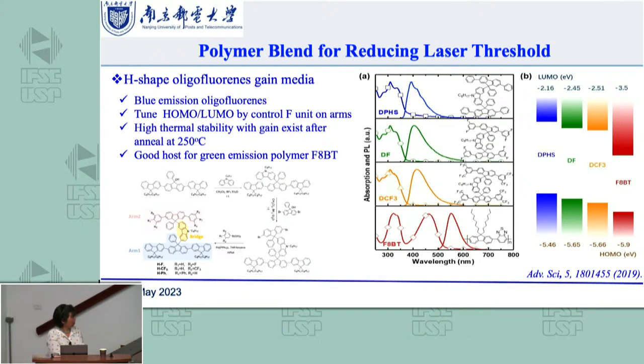And another thing is, because we have the H-shaped material, we think about using energy transfer. The idea is if you look at the spectrum of this, this material has absorption here and emission here, and this one absorption, emission. And this is another polyfluorene we call F8BT that gives the green-yellow emission. This absorption here, if you look at this peak, it almost overlaps with the emission part of this group of material. So in that case, we think energy transfer could happen from this material to this if we put these two materials together. So use that as a host and this as a guest.